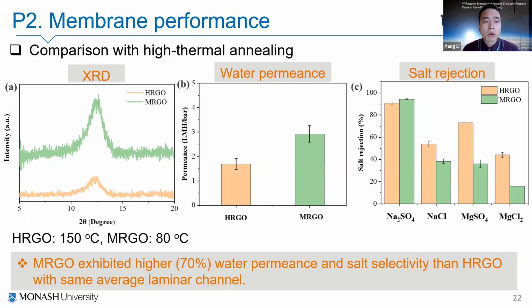One thing we want to know is the advantage of melt annealing compared to high thermal annealing. So we prepared another membrane under the same condition, except that the thermal temperature is much higher. And we compare these two membranes with the same interlayer distance. We found that, compared with the high thermal treatment one, the melt annealing reduced RGO membrane shows both a higher water permeance and a higher selectivity.